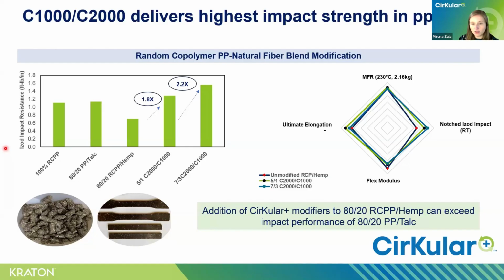So we've used as the baseline an 80 to 20% ratio of random copolymer polypropylene and talc. And then we introduced two Circular Plus formulations in different ratios. So a 5:1 ratio of C2000 to C1000 and a 7:3 ratio of C2000 to C1000. So if we look here at the impact resistance, the trend is very clear because both formulations exceed the impact strength of the baseline blend, and the radar chart further shows the improvements across the key properties such as ultimate elongation, flexural modulus, melt flow rate, and impact resistance.